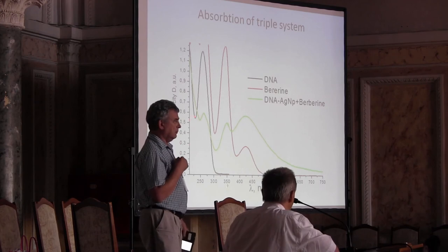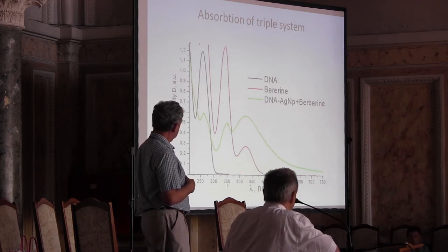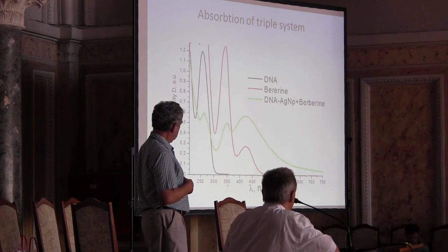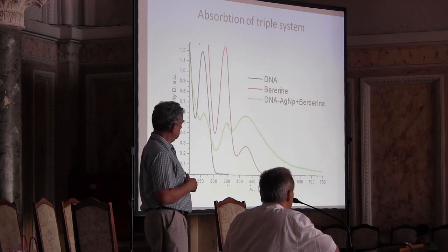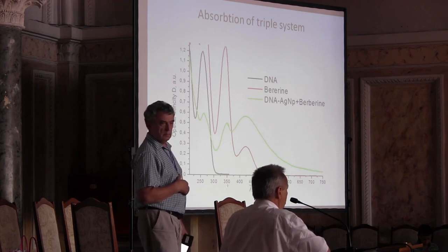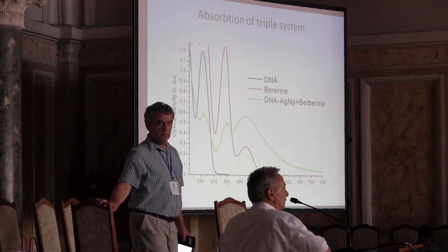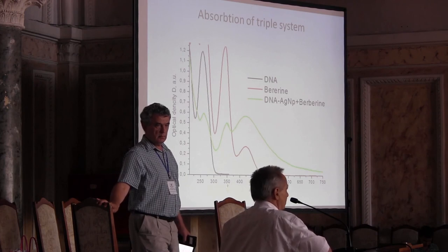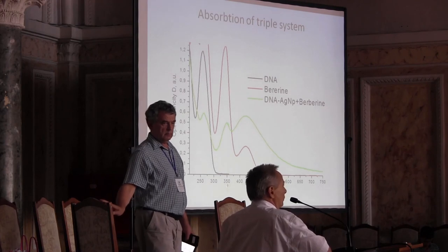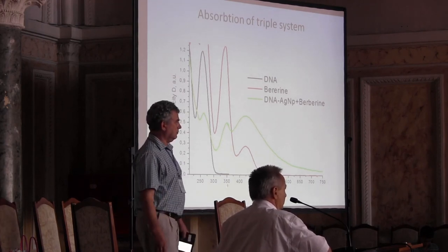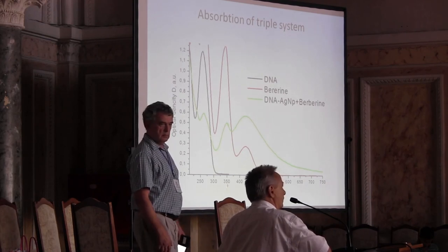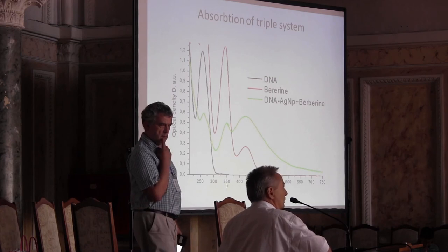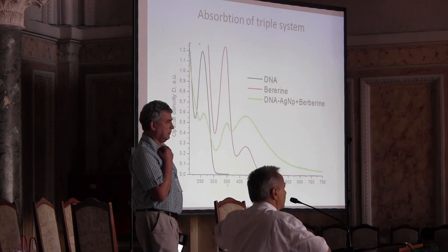And from here you see the berberine band, and you see here the deformed, changing band. So we proved that berberine binded to DNA because of the intensity increase, and the method of preparation of nanoparticles includes that argentum nanoparticles are growing on the DNA as template. So this is additional proof.